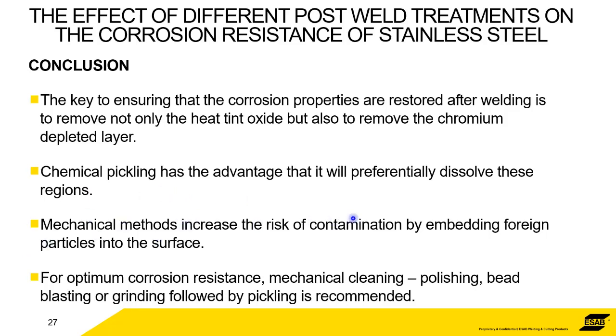Mechanical methods, yeah, fine, absolutely, if that's all that you can do. But you do have the risk of embedding particles in the surface, so you have to be sure that it's nice and clean once you've finished doing any kind of mechanical grinding, polishing, machining. They're all risk points for damaging the surface and damaging the chrome oxide layer. So providing you can restore the chrome oxide layer, then this is fine. You can do that by leaving it in air. You can do that by passivation, for example.